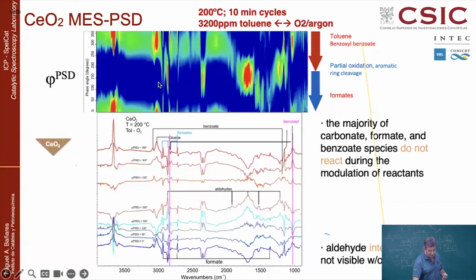And then, after you do that, you can tell all the components apart. So you also can represent this psychedelic drawing like a two-dimensional plot, where the red things will be positive peaks and the blue things will be negative peaks, or vice versa, whatever. So then you are doing the reaction with toluene, and then you see that here in red these bands are increasing, that band was decreased and increases later on, and this is the phase. So basically during half of the cycle you are feeding toluene and air, and during the other half of the cycle you only feed air.